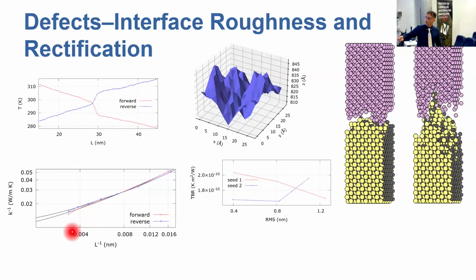In this case, we plotted the inverse thermal conductivity with respect to the inverse junction length, and then we performed a linear fit. This allowed us to extract the thermal conductivity of the junction in the forward and reverse condition at infinite length, which corresponds to length to the -1 going to 0. From this, we observed a thermal rectification coefficient of around 30%, which is a pretty fair value, and that could allow some technological applications.